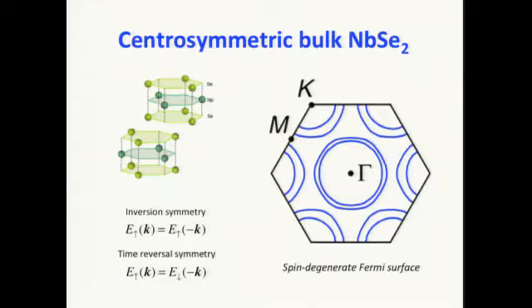Okay, so to understand the superconductivity in this material, let's first turn to the normal state of the material. In the bulk niobium diselenide, it's inversion symmetric with the inversion center between the layers. You flip the material upside down and it goes back to itself. So if we perform an inversion symmetry operation, flipping k to negative k without changing the spin, the energy of this Bloch state should be the same. If we perform a time reversal symmetry operation, flipping k to negative k and spin up to spin down, the energy still has to be the same because the material obeys time reversal symmetry. With these two conditions, the Fermi surface is fully spin degenerate at every point in momentum space.